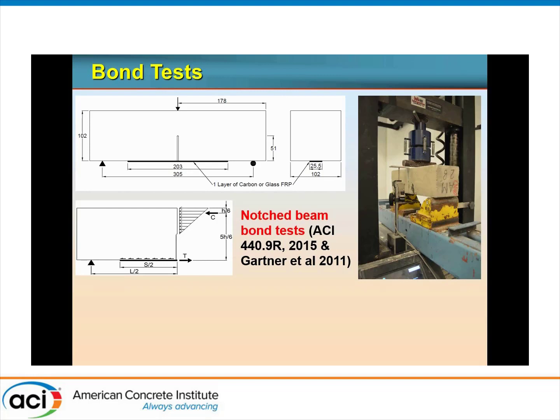In this case, we actually used the notched beam bond test, which was developed earlier by Gartner and Trey Hamilton and their group, and later adapted by the ACI 440.9R, and it's part of the testing protocol for bond. I find it an excellent method in that it gives you a quick, simple, comparative assessment between different products. It captures an average bond strength: you could simply use the internal forces, get the force T, and divide it by the bond surface area. You get an average bond strength to concrete. So that was the method we used.